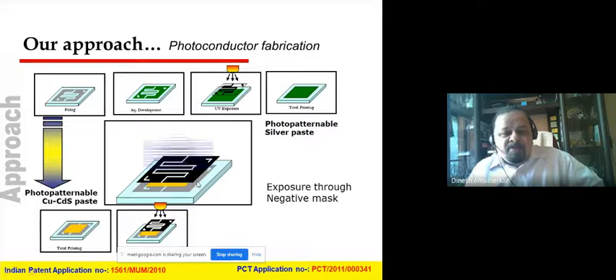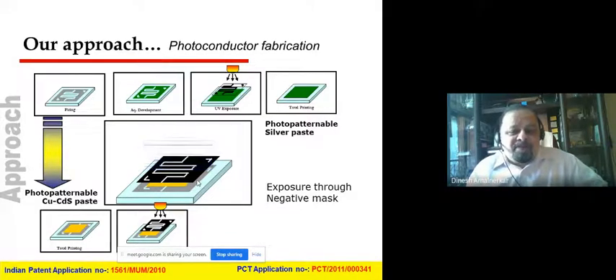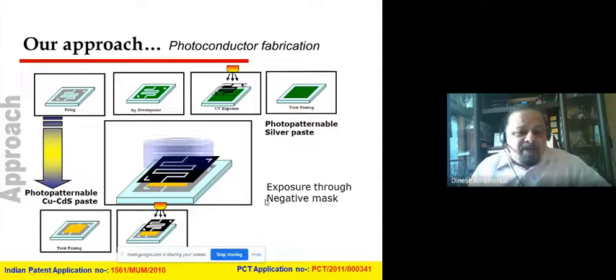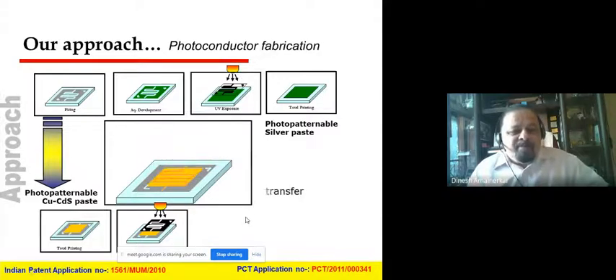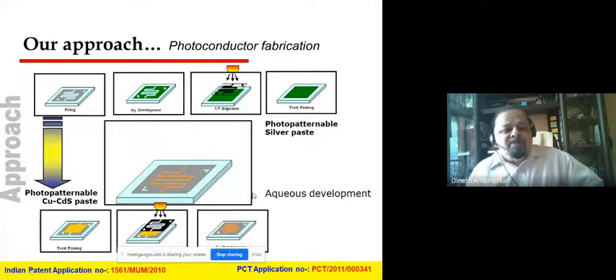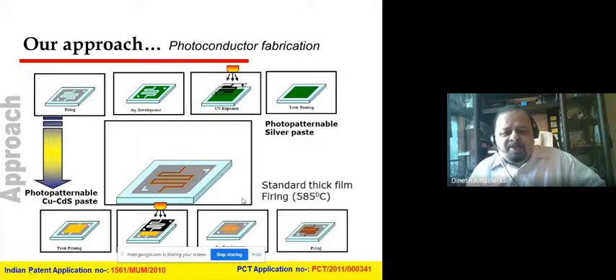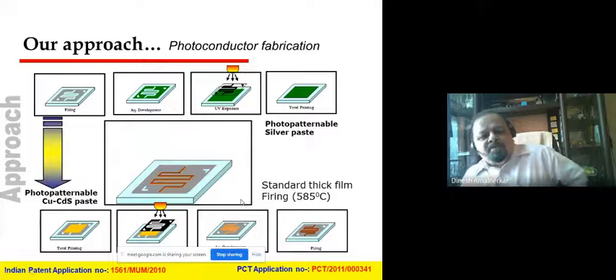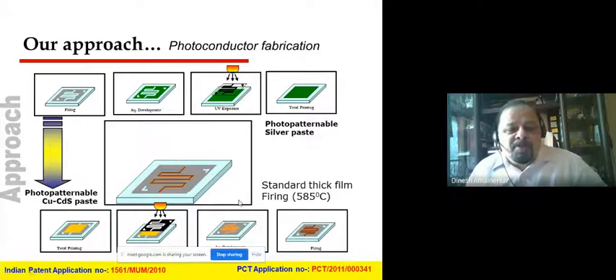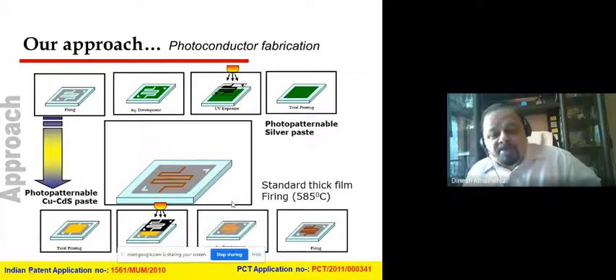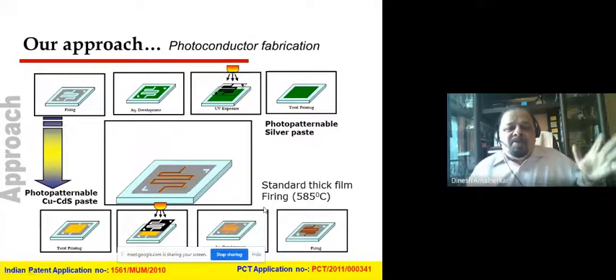But this time, we use the negative mask for exposure to UV light. The negative mask is the exact replica of the earlier one, so that wherever this space is available, the material gets hardened after UV exposure, and the remaining cadmium sulfide can be removed by aqueous development treatment, and then it is subjected to firing at 585 degrees centigrade for 10 minutes to mature the photopatterned cadmium sulfide in this particular device. Now our device is ready.